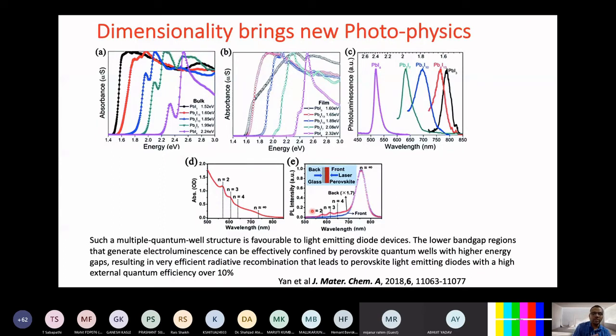When you have 1D, then you have fixed energy states, and when you have 0D, you have delta functions. So the density of states versus the dimensionality is shown here. For n equal to infinity, you see the spectrum follow the E to the power half relation. But the moment it goes beyond that, you see this staircase structure which corresponds to the 2D character.